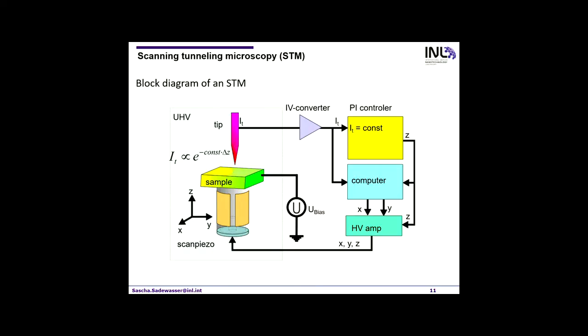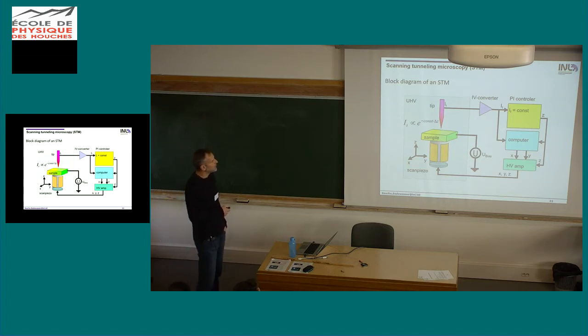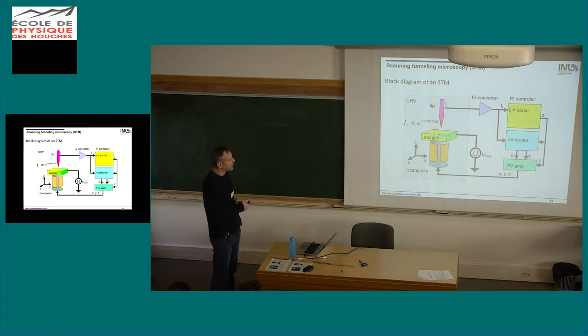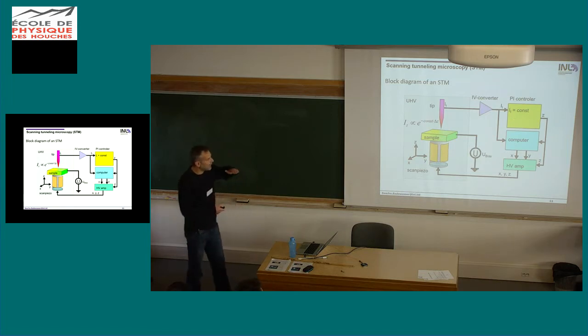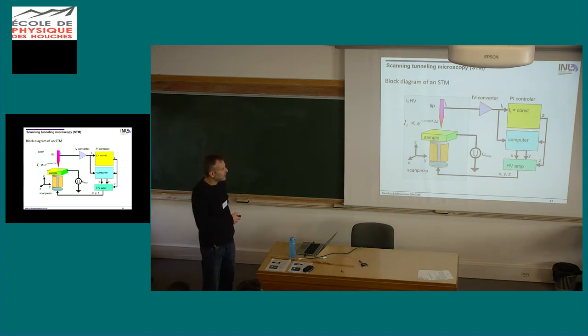So how is it built? This is a typical block diagram, very simplified, of a scanning tunneling microscope. We have the tip, of course, we have the sample. Then we need to scan the sample very precisely. For this we use a piezo scanner, and I will explain all of these elements in the following slides. Then what we need is a current voltage converter, to look at the current that comes from between sample and tip. We have a controller that controls this current to be constant, and that at the same time gives our tip height signal, which we feed into a high voltage amplifier to apply to the piezos. And on the other hand, we have a computer that records all our signals and controls the scanning.